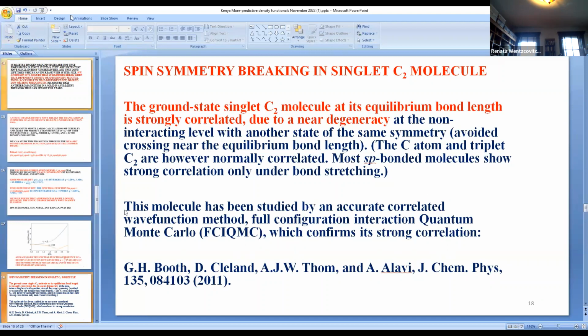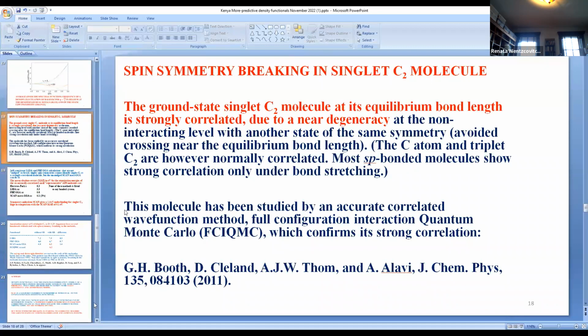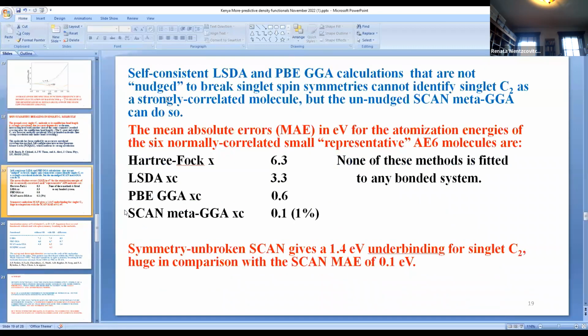If we do self-consistent LSD and PBE generalized gradient approximation calculations—the first and second rungs of Jacob's ladder—without letting them break symmetry, and typically the only way to get a system to break symmetry is by nudging it into the symmetry-broken state, then if we don't do that nudging and don't allow symmetry breaking, these functionals don't identify singlet C2 as a strongly correlated molecule. That's because they're not accurate enough.